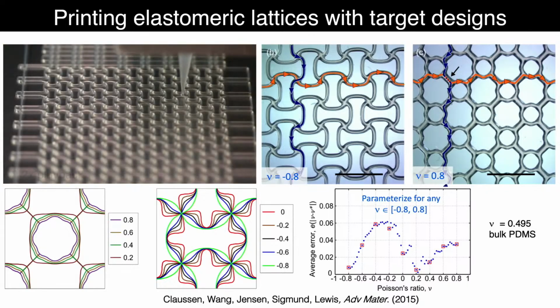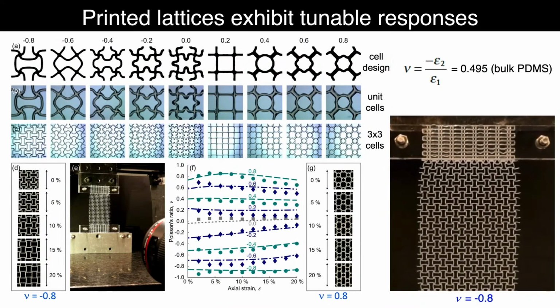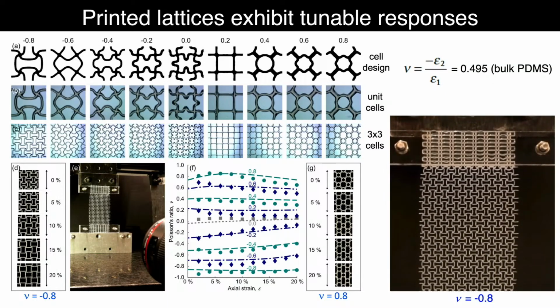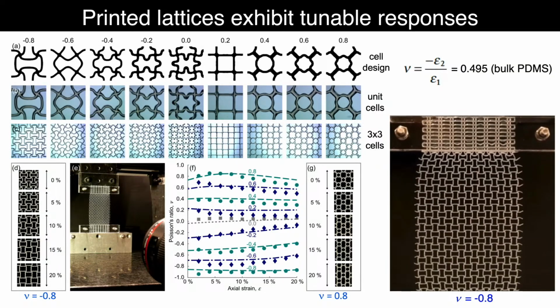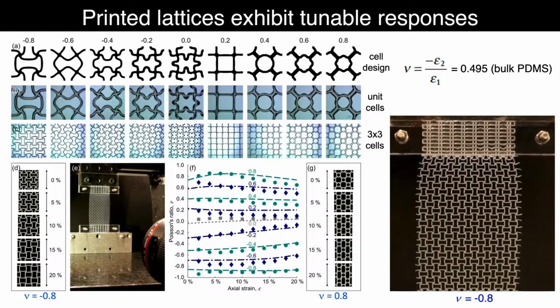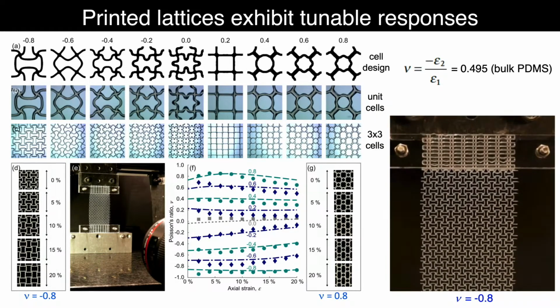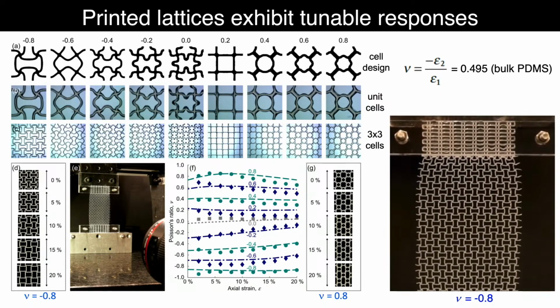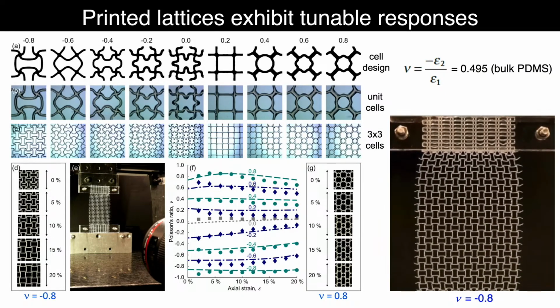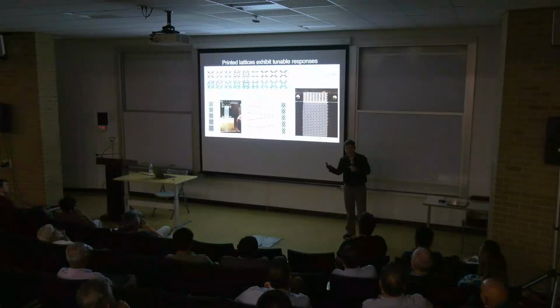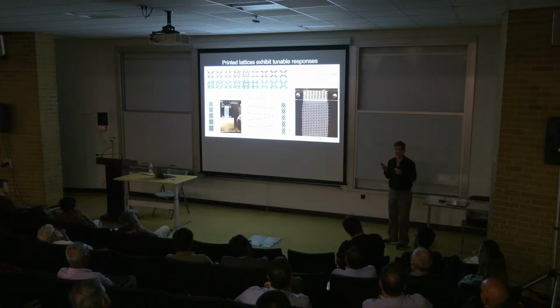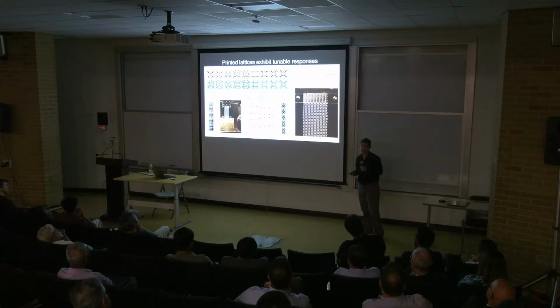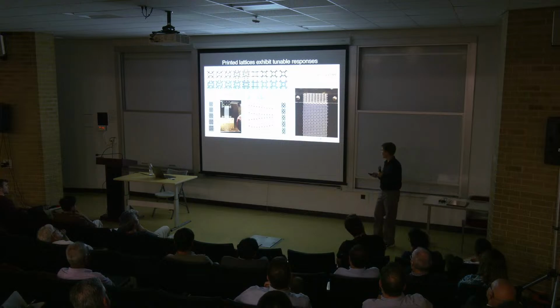But a priori, we can design over this broad parameter space simply by changing the unit cell architecture. You can see this very nicely here, how the unit cell design changes, and concomitantly how we get a variation in the Poisson ratio. As this structure is expanded under uniaxial tension, it is also expanding in the lateral direction, which is why you have this negative Poisson ratio. As we go to different lattice unit cell designs, we can dial in anything from -0.8 to 0.8 in terms of the Poisson ratio. And of course, using things like embedded printing, which I'm not going to talk about today, one can take this into the third dimension. There's work here by Tim and others that are doing beautiful three-dimensional architectures. But I think this was one of the earliest embodiments of using printing to a priori design, control, and program the mechanical response.